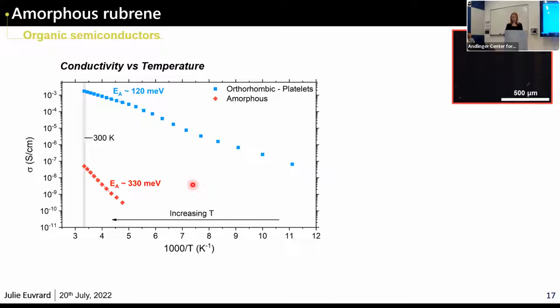First, conductivity. You have the data for amorphous in red here. The first thing you can notice is that at room temperature, the conductivity is almost 5 orders of magnitude lower than polycrystalline. This shows you how order can be important because it's the same molecule and the order has a dramatic impact, which is actually quite reminiscent of what we see in silicon, where we also have many orders of magnitude difference between the conductivity of amorphous silicon and crystalline silicon. The behavior with temperature is what we expect for hopping transport.